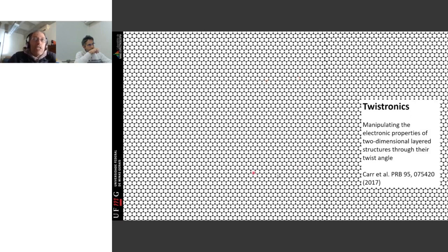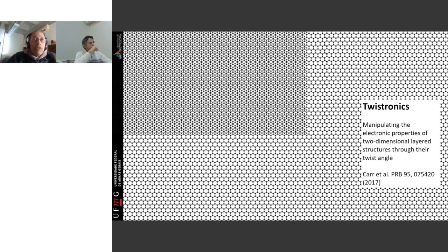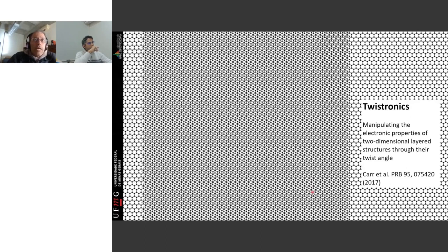What you see here is a graphene sheet. Every black bullet here is a carbon atom bound to each other in this hexagonal structure. Let's place another graphene sheet on top. Okay, this is a bilayer graphene, okay? And the bilayer graphene, the most stable situation, this is what you find in graphite, is when one of the atoms in the top layer falls exactly in the middle of the hexagon of the bottom layer. This is called AB stacking, okay?